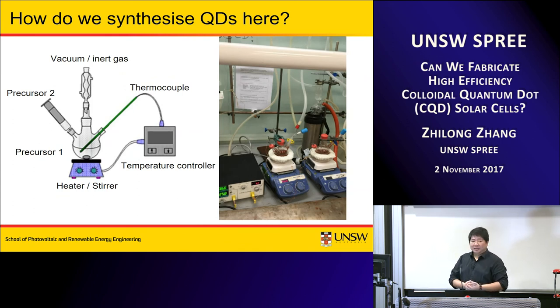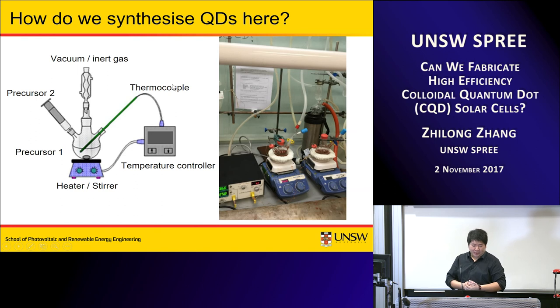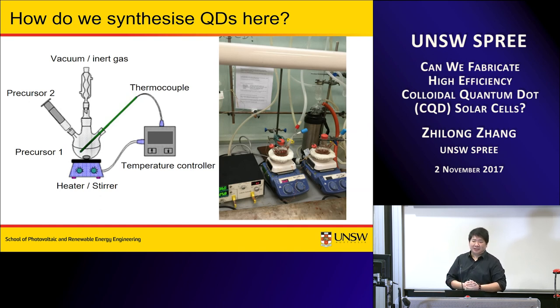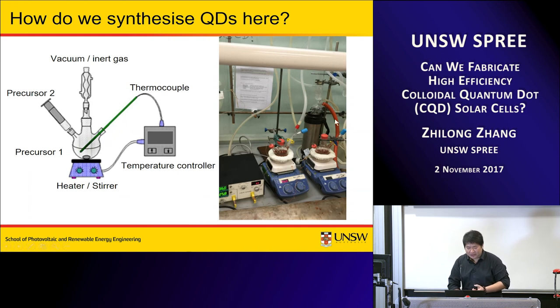How do we synthesize quantum dots? We actually synthesize them just upstairs on the first floor. We use the hot precursor injection method. We have a reaction vessel with multiple necks — one end connected to a vacuum manifold to remove moisture and air. A thermocouple controls the temperature of one precursor, and when it hits a certain temperature we inject the second precursor — for example a lead precursor and a sulfur precursor. By controlling the mixing temperature we can control the size, luminescence, and absorption. The photo on the right shows an actual setup of this schematic, which we run in our lab.